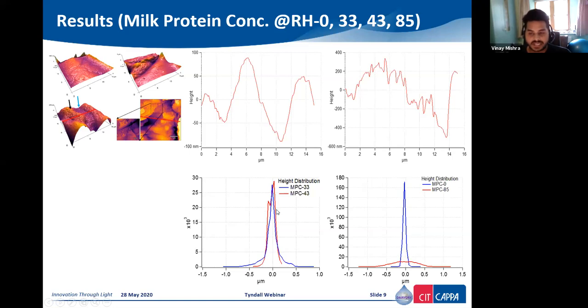You can see as there was less lactose, and that was in the subsurface of these particles, there is no major lactose crystallization happened on the surface. That's why we have almost similar and narrow height distribution just before the moisture required for lactose crystallization, and after that. Again, you can clearly see in the plots in the height distribution when I'm comparing the results of MPC 0 and 85 that the height distribution is changed. And again, I wanted to mention that this is because the protein on the surface has changed rather than lactose, because it's in the subsurface.